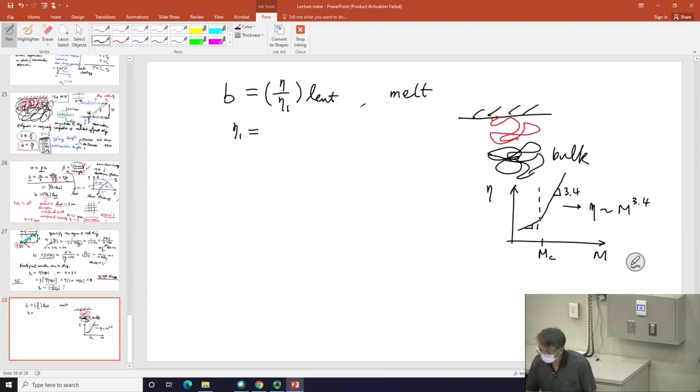And this strong molecular weight dependence, we even went through it. It is due to the fact the chains are having trouble moving because there are many other chains here, so they are trapped in a tube. And that's the origin of high viscosity. Well understood, no debate.